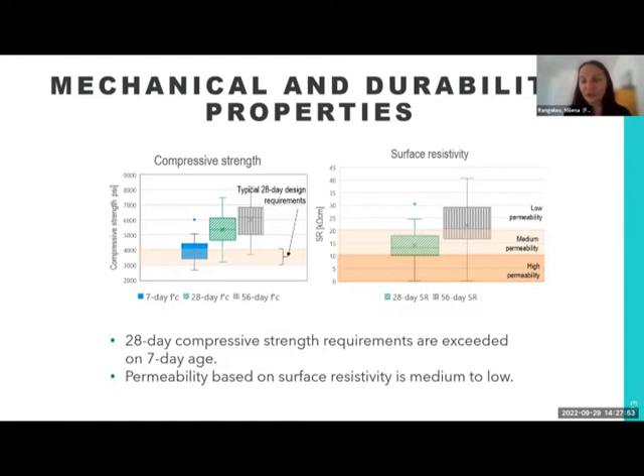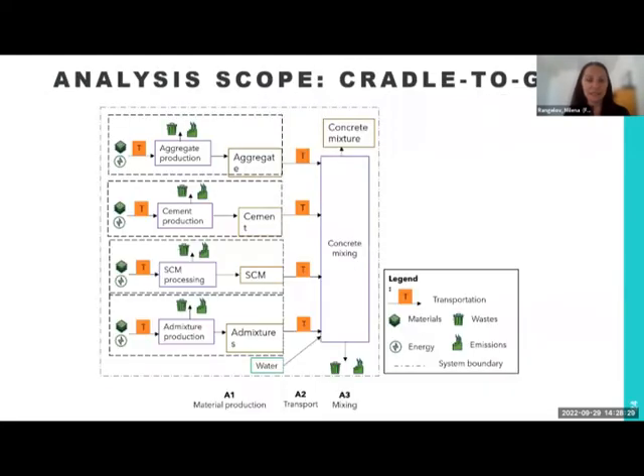There are several reasons for that. One is that contractors are typically penalized if compressive strength doesn't pass, so they do tend to add more cement to their mixes just to make sure that they don't have any penalties. However, that is increasing the cost of the mix as well as creating some durability concerns. On the right-hand side is surface resistivity. That's not analyzed in this study per se, but we have a new study that is coming up where we analyze surface resistivity and sustainability correlations in detail.